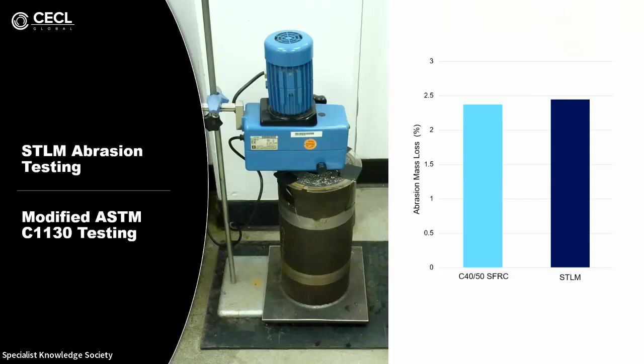So abrasion is another durability concern, particularly for hydraulic tunnels, and we've undertaken a modified version of the ASTM C1130 underwater test. This is where a sample is submerged in a steel tube. We put some varying sizes of steel balls on top. It's underwater. A motor and a paddle spins this arrangement at 1200 RPM to generate an abrasive action. We leave that running for 7 days, like a mini washing machine. And we measure the mass loss from the samples because of that abrasion. And we found comparable performance to fiber reinforced structural concretes.